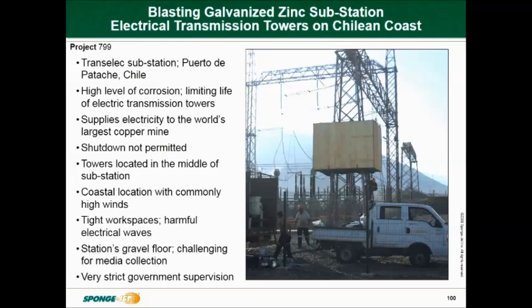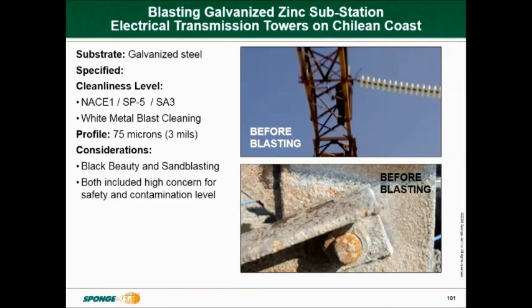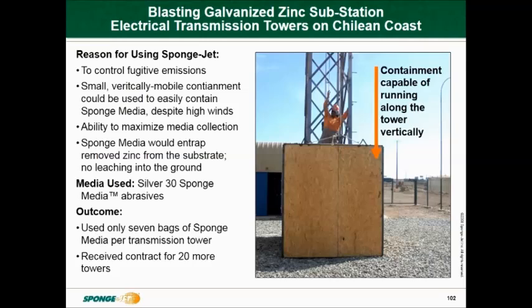Project 799, transmission structures and the substation attached to the power station. All of the work on these towers were performed while the unit was live, and they did design an easy containment box, and it was constructed around the towers and it could be elevated as required. The galvanising was at stage 3, shown in the matrix earlier, which was a heavy flaking rust. They used silver 30 to perform this application blasting on the galvanising. For transmission towers, I recommend that silver 60 or even less, an 80 grit, because we don't need to remove the galvanising, just remove the condition on the outside.